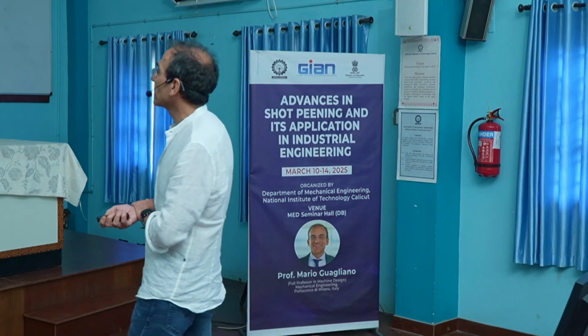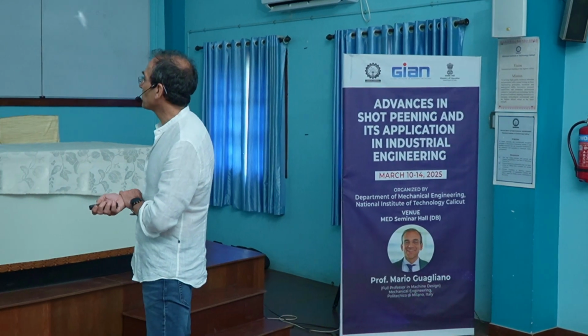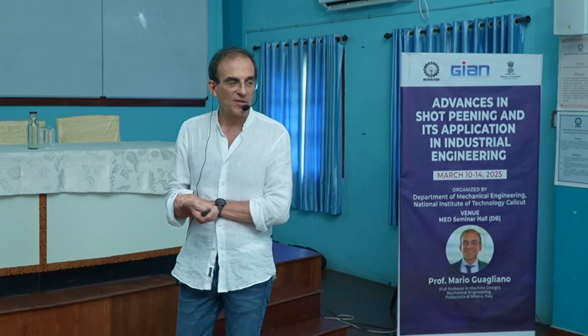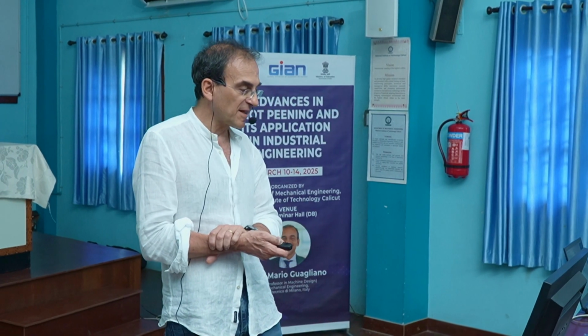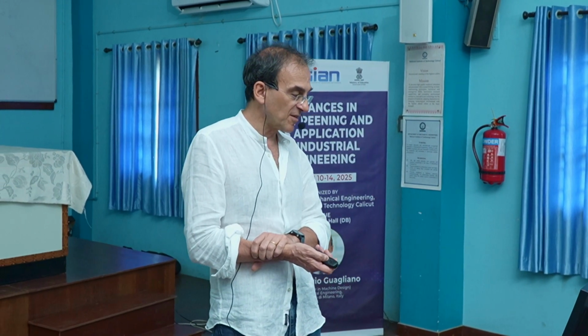And this is the final slide, where we have advantages and disadvantages. We have already discussed the pros and cons of the techniques we have considered, hole drilling and X-ray diffraction. Hole drilling is quick, simple, portable, widely available, and deep hole drilling suits thick section components. On the other side, the interpretation of data could be unclear, it is destructive, and it has limited strain sensitivity and resolution.